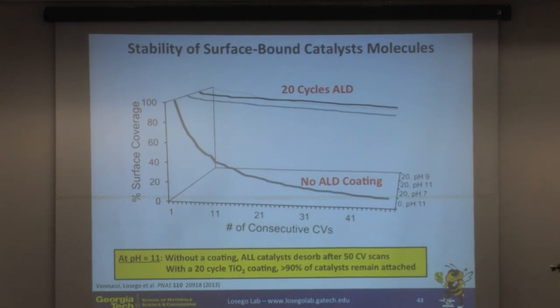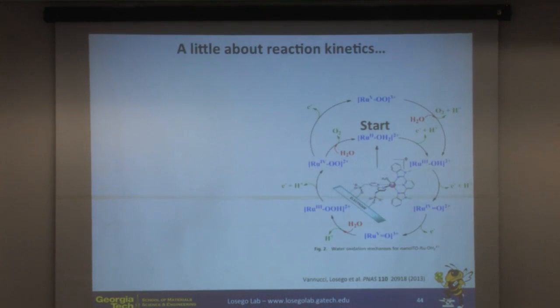So this is just a plot of surface coverage from integrating the redox couple, that CV curve. We can track the percentage of molecules on the surface as a number of cyclic voltammetry cycles. With no ALD coating, we see loss of surface coverage. With an ALD coating of the optimized 20 cycles, we see great stability for a variety of pHs, from neutral pH up to a pH of 11. Now this is important because we can actually access different reaction kinetics based on the pH we're working at.